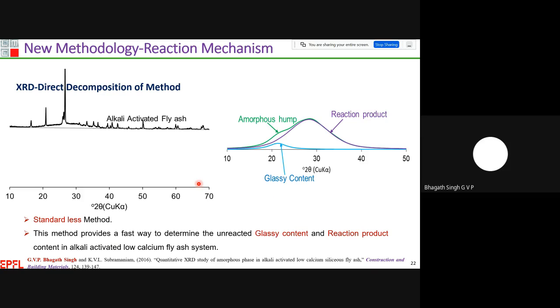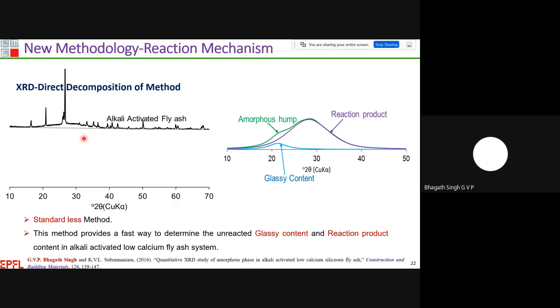And to overcome this, I have developed a new XRD based direct decomposition method. I'll quickly go through this methodology. This is the XRD spectra of alkali activated fly ash, in which I can see different crystalline phases. The same XRD signature which I have shown here, I have used here, with different crystalline phases along with the broad amorphous hump.